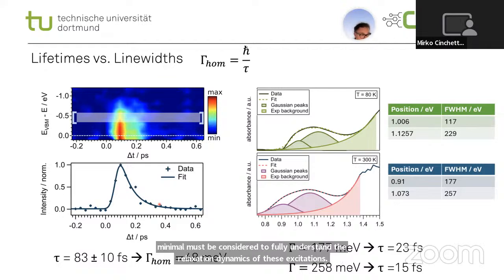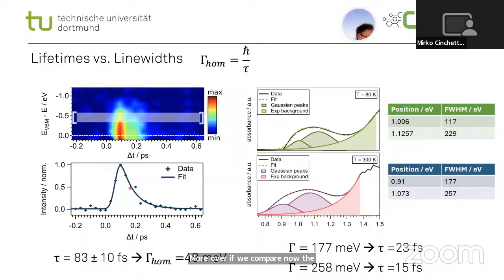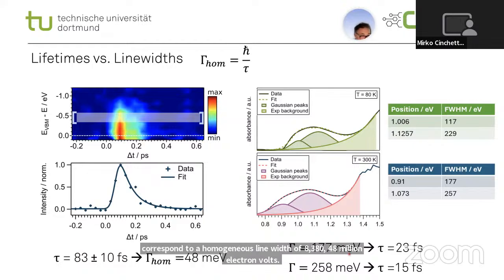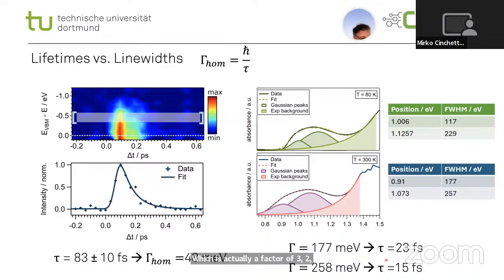Moreover, if we now compare the lifetime to the line width measurements, 83 femtoseconds would correspond to a homogeneous line width of 48 milli-electron volt, which is actually a factor of 3 to 4 times narrower than what we actually measure in the optical absorption experiments.